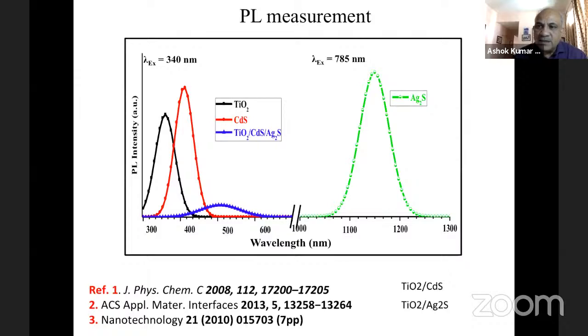Now you can see the way you can measure photocurrent, you can measure photoluminescence to see how effective the core shell structure is and how effective it is to enhance the efficiency. So one of the things I told is that when you create charge carriers on the surface of the semiconductor, the charge carriers should not recombine very easily. So the lifetime will be higher. And if it doesn't recombine, that means you will not have PL. So your PL intensity will go down.